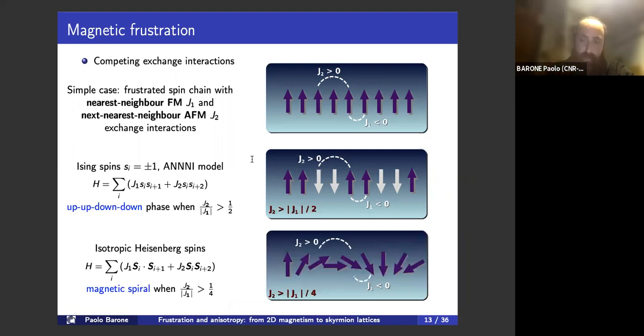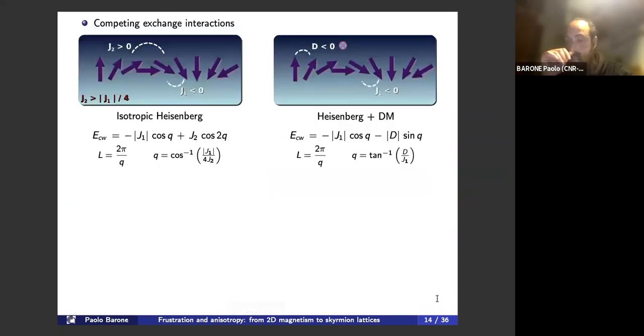Now, if we have instead Heisenberg spins, we have a similar thing. So we can break the collinear phase that one would expect from simple isotropic non-competing interaction, stabilizing then a magnetic spiral, again above a certain threshold for the ratio between the two competing interactions. And let me stress the fact that, of course, as we have seen before, the Dzyaloshinskii-Moriya interaction is also responsible for such non-collinear coplanar phases. And there are two main differences when comparing spirals induced by competing exchange interaction and competing Heisenberg-Dzyaloshinskii-Moriya.